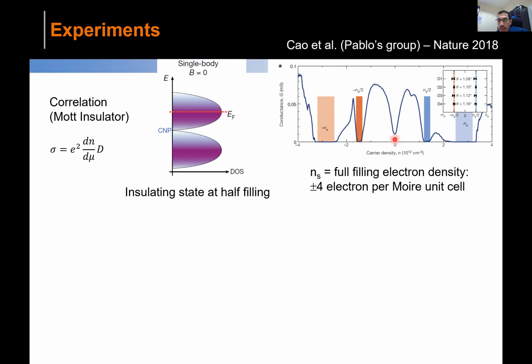What they see is that when you dope the system away from zero, the zero point being the charge neutrality point, you reach the full filling of the band, which is here. You have a gap because there is another higher band, so there is no state here, and that's the reason your conductance goes to zero. But interestingly, at half filling, which is at this point where you have the maximum single-particle density of states, it turns out the conductance goes to zero. You cannot explain this by a single-particle picture. So what is happening in this kind of system?